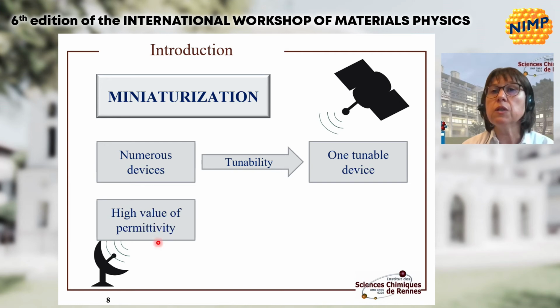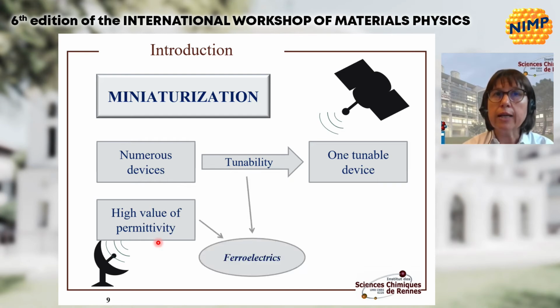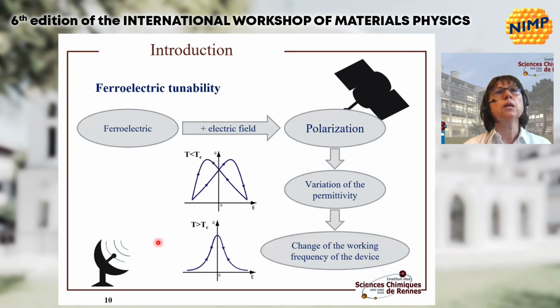High value of permittivity in the device, in the substrate itself or sublayer, will give the possibility also to miniaturize in high frequency. Ferroelectrics give both tunability and high value of permittivity. And depending on the operating temperature, the material will be in the ferroelectric or paraelectric phase, giving the possibility to modify the permittivity, epsilon, with the application of an electric field. And in this case, the evolution of the permittivity will give the possibility to tune the device, for instance, by changing the working frequency of the device.